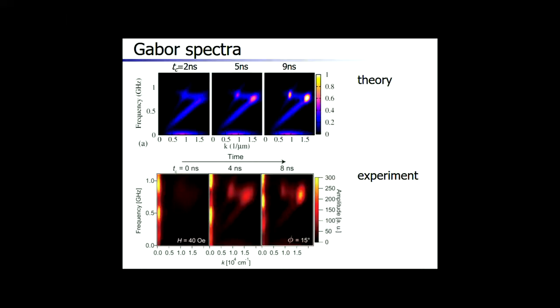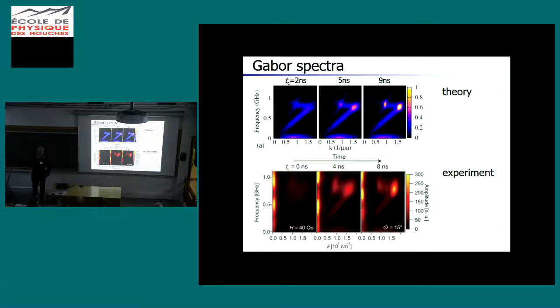Now, that's an interesting technique also developed by Hashimoto, which is called the Gabor Spectra, in which you look basically at the Fourier transform as a function of time. So it's a sort of a mixed representation of the real space and reciprocal space. And here you see as a function of time how, for example, these crossing points, these magnon-polarons, develop for the small spot sizes, and we get a very nice agreement with the experimental results in this case.